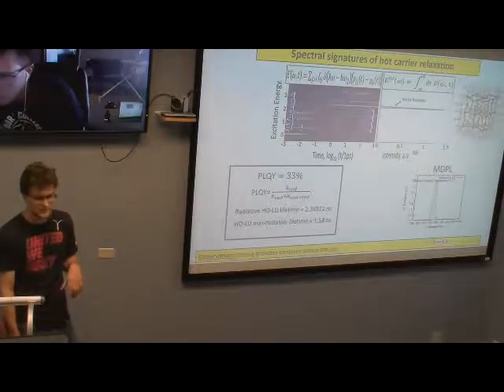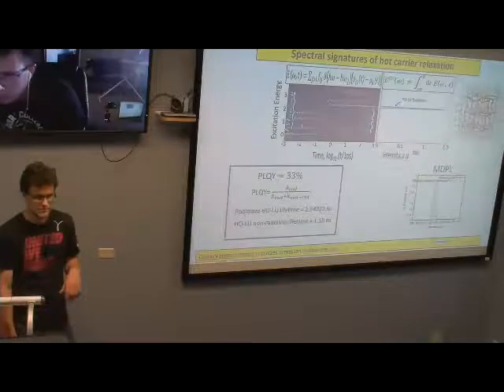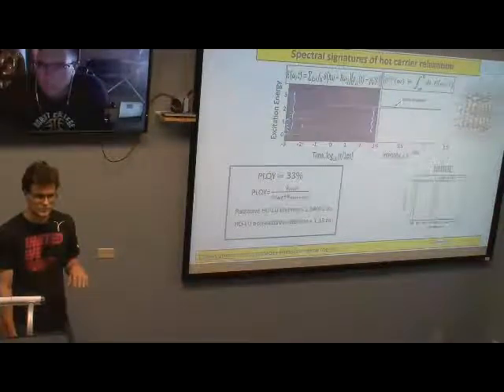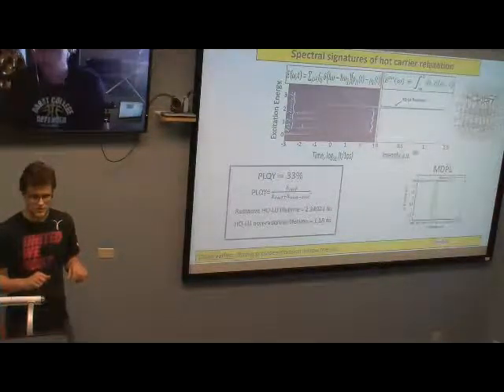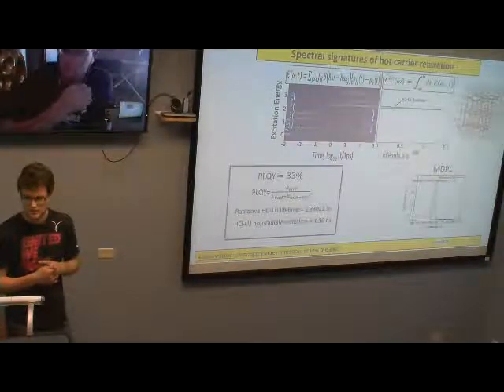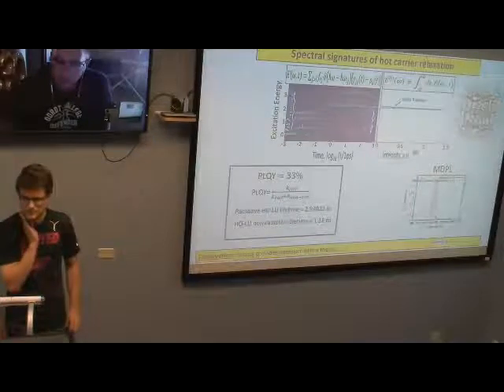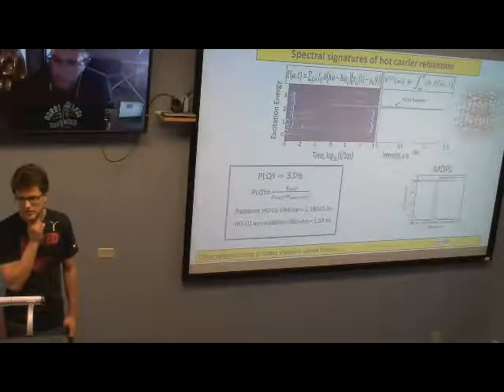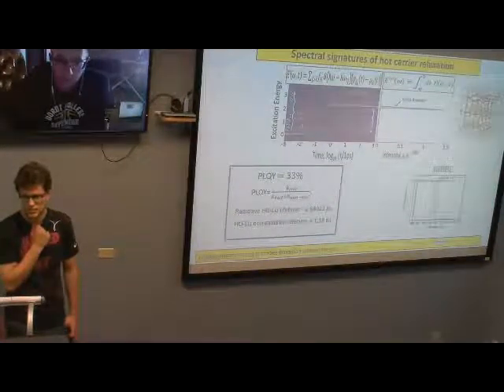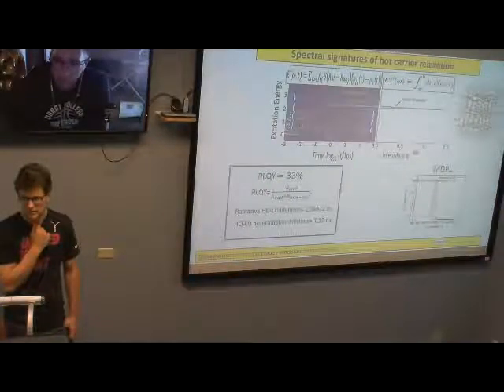It's a little broad. So one explanation I've heard thrown around is that the temperature in VASP, or for your molecular dynamics trajectory, doesn't necessarily correspond to physical or real temperatures. I haven't looked into the paper. I think Dimitri referenced the paper. There is Maria Fernandez Serra from Stony Brook University. And she found that in order to model 300 Kelvin in reality, you need to run simulations at 250 in DFT, but this scaling depends on the functional, so it is for PBE.